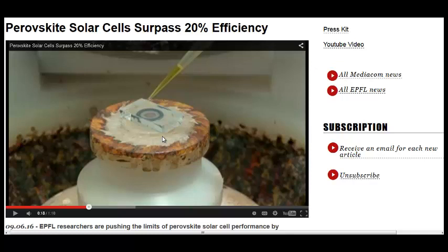This breakthrough is very simple — they just change the pressure at which the cell is processed. They put a solution onto a conductive material, in this case glass, they spin it, and then they put it in a pressure chamber at a very specific pressure. They were able to get a crystal that grows and can conduct and capture 20% of solar energy.